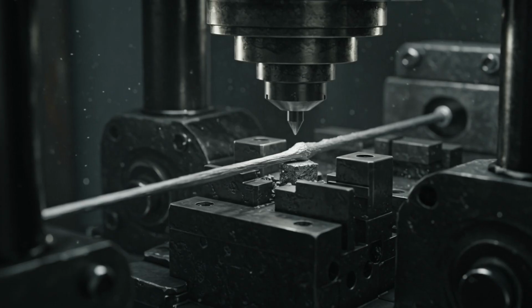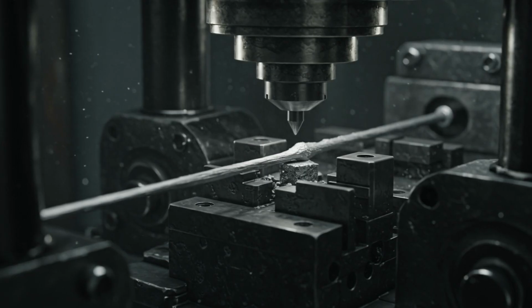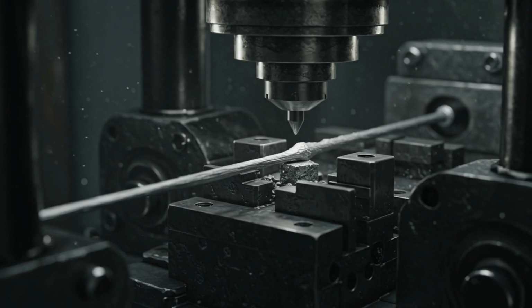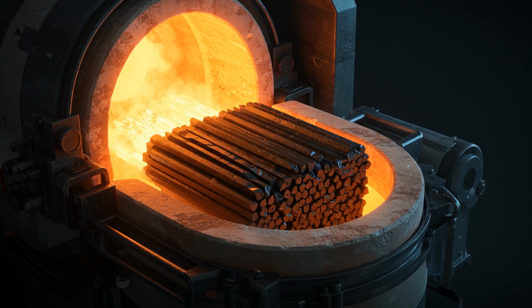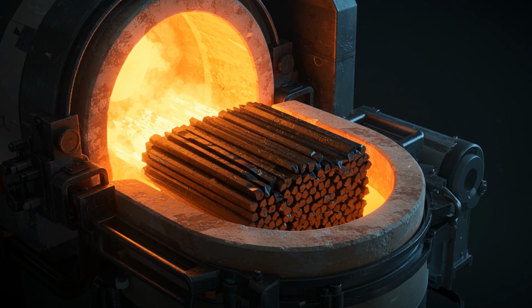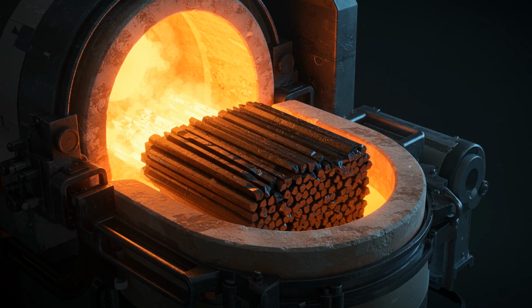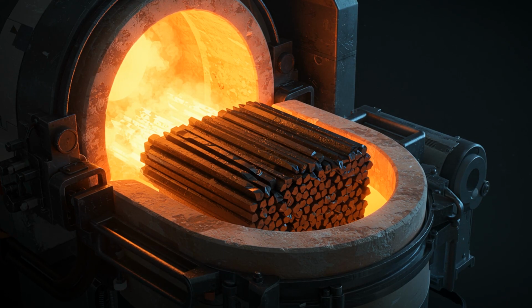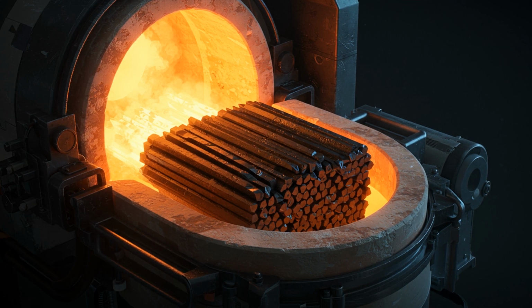To transform this brittle clay-carbon mix into a rock-hard writing tool, we must harness the power of extreme thermal energy. The leads are packed into sealed crucibles, prepared for a journey through the heart of a furnace that mimics the conditions found deep within the Earth's crust. Inside the kiln, the temperature climbs to a staggering 1,800 degrees Fahrenheit, or approximately 1,000 degrees Celsius. This is the sintering process. As the heat intensifies, the kaolin clay particles undergo a chemical transformation, fusing together to form a hard ceramic latticework. This matrix traps the graphite flakes in a rigid structure. Without this step, your pencil lead would simply crumble under the slightest pressure.